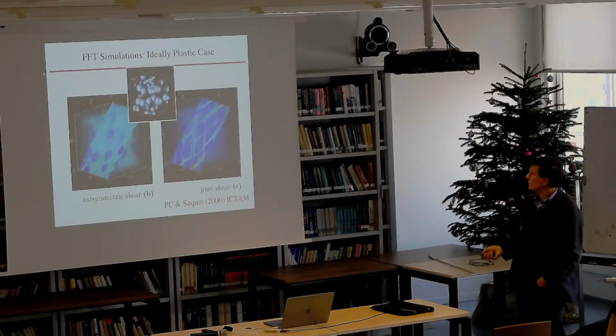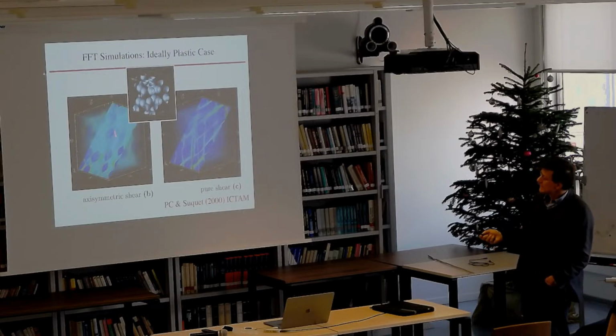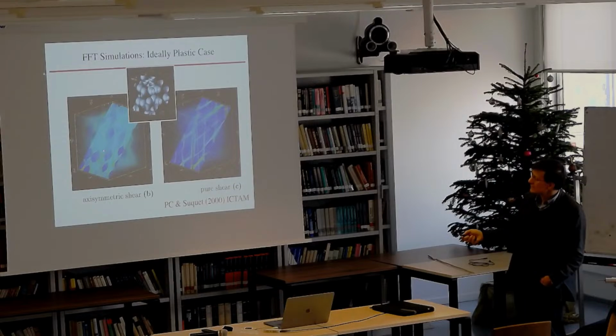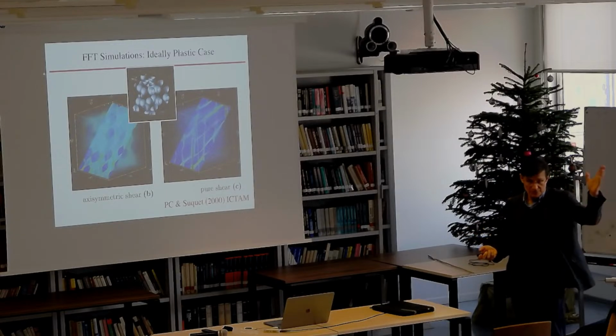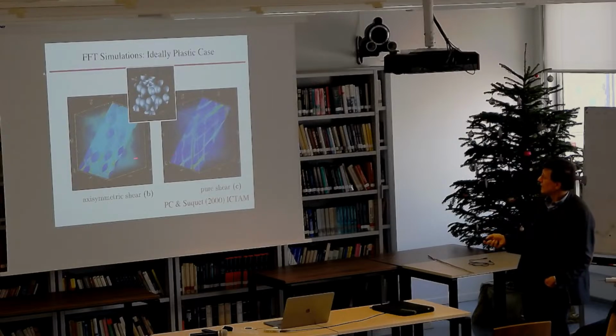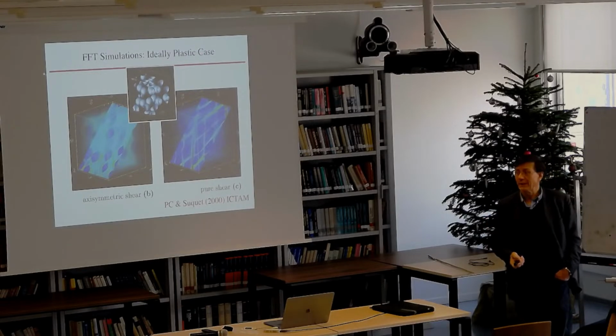And in fact, we've known for a long time - these are some FFT simulations, early FFT simulations from the group in Marseille. This is axisymmetric, and this is pure shear. In one case, the fields in the suspending fluid, which in this case is ideally plastic, are uniform, more or less uniform. These are the strain rates. Near the particles, you have some intensification, especially when the particles are close to each other - this is what we were talking about before. But otherwise, the fields are fairly uniform. When we go to pure shear, the fields localize on these very sharp bands.